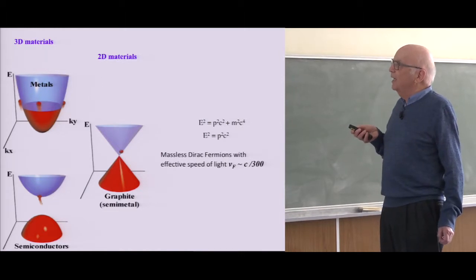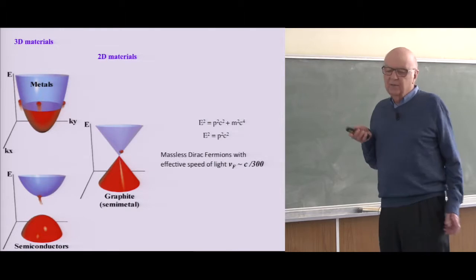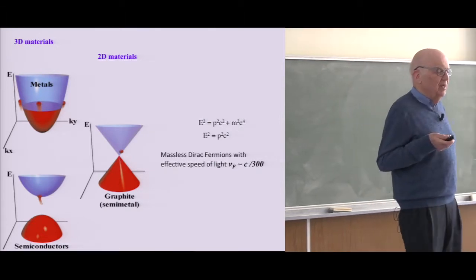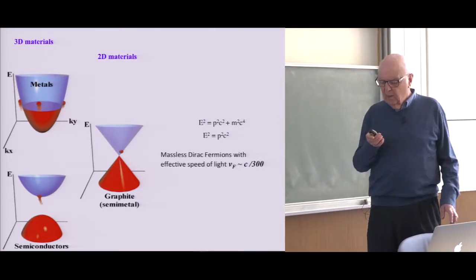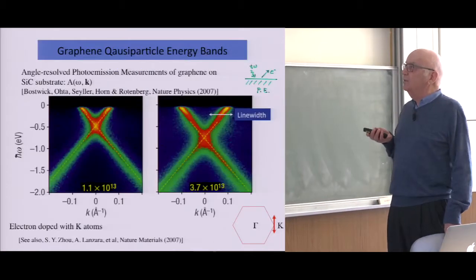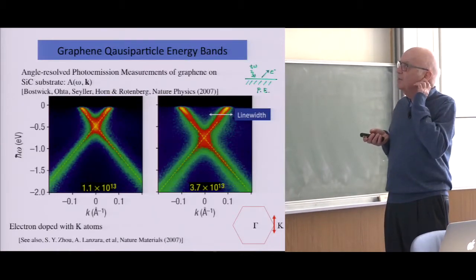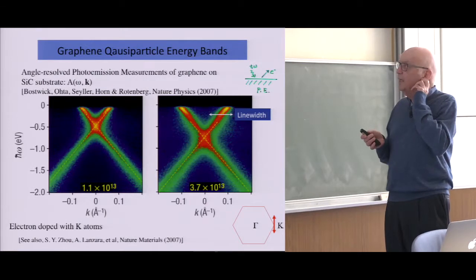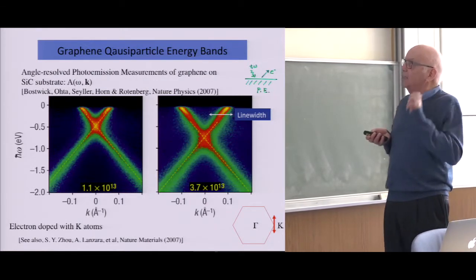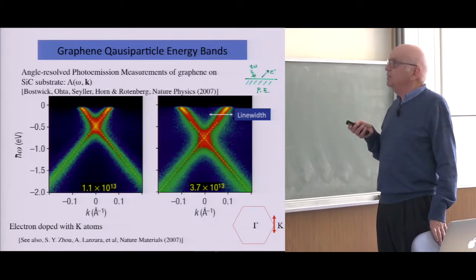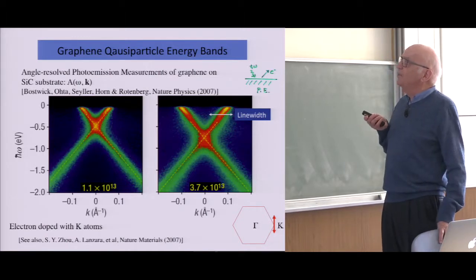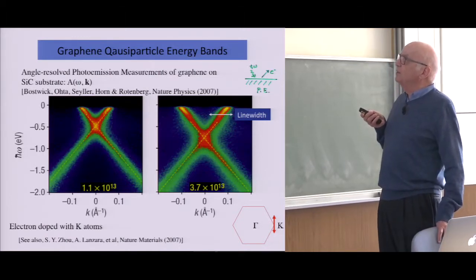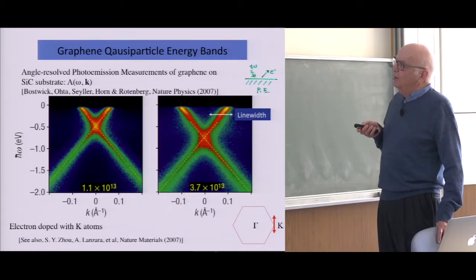And so it looks like massless Dirac fermions with an effective speed that is 1/300th of the speed of light. And those properties allow you to do many things. Now, the first thing is, what about experimentally? And what I want to assure you is that this has been seen. So for angle-resolved photoemission, you shine the light in, electrons pop out, and you can plot the band structure.